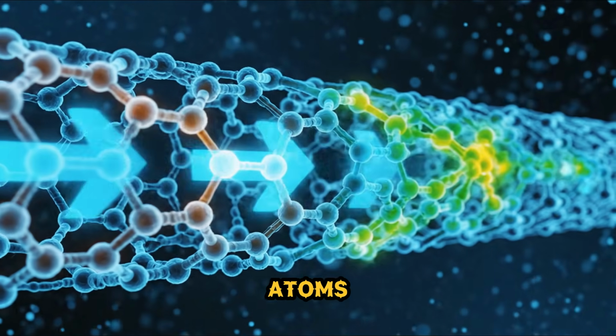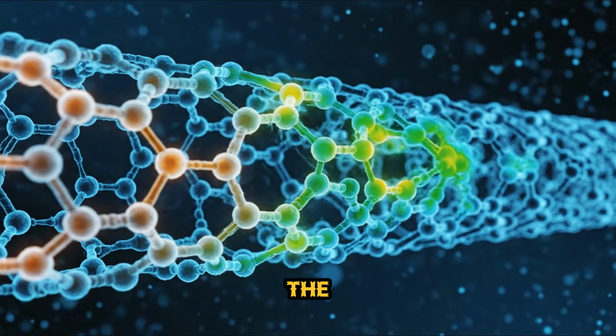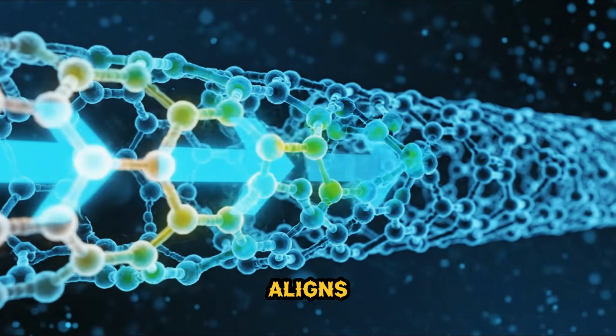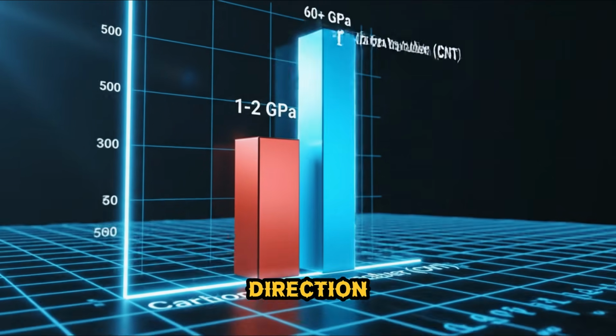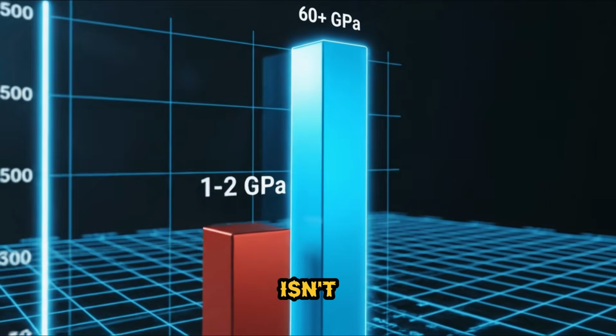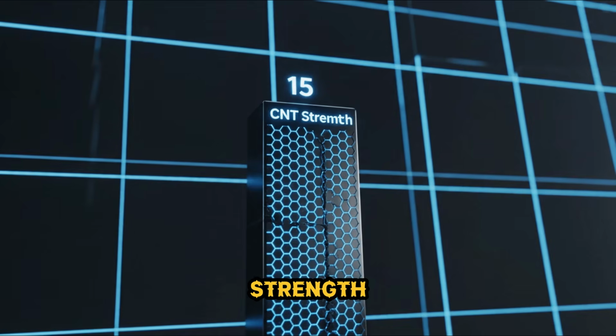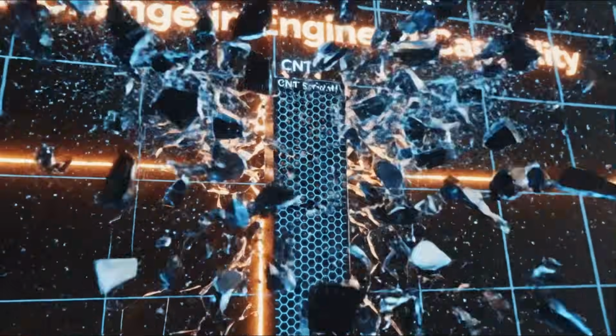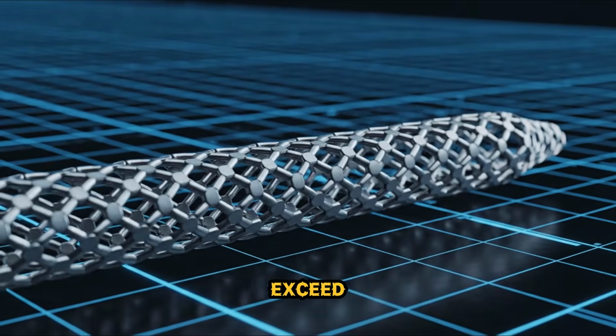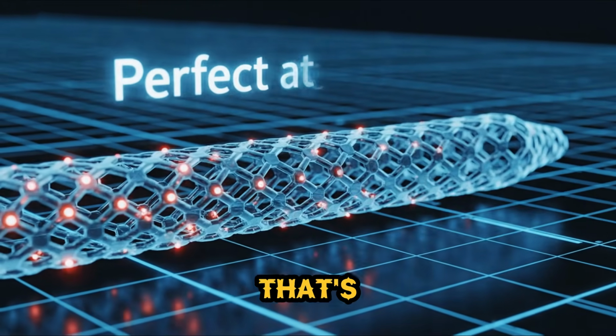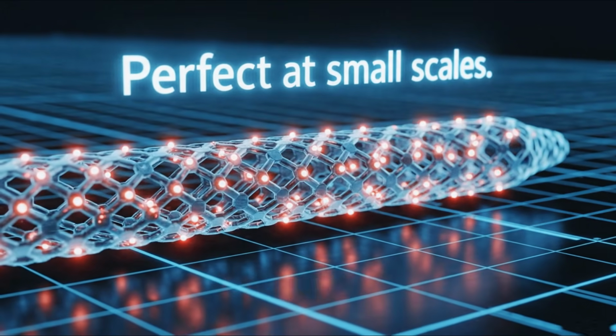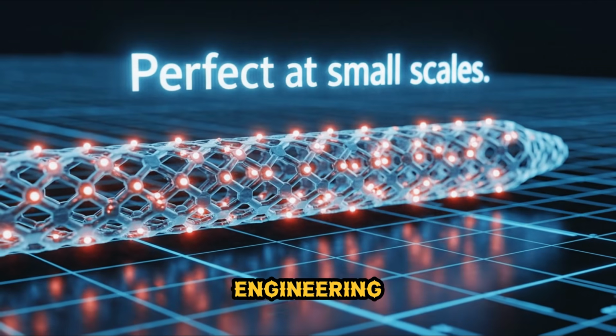Because when carbon atoms bond in this configuration, the strength of the covalent bonds aligns almost perfectly with the direction of applied force. This isn't just a strong material. This is near theoretical maximum strength, dictated by quantum mechanics. To put that into perspective, steel fails at around 1 to 2 gigapascals. Carbon nanotubes exceed 60 gigapascals. That's not an incremental improvement. That's a phase change in engineering capability.